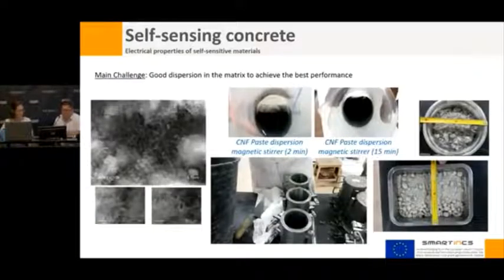The incorporation of a component into the cement matrix to provide a new property very often leads to a modification of its properties. Additives such as CNT and CNF would preferably modify electrical resistance properties, but microstructure and, as a consequence, mechanical properties can also be affected, in both fresh and hardened state. If a lack of dispersion or interfacial interaction with the cement paste occurs, the effect can depend not only on the additive content but also on the characteristics of the composite matrix. The introduction of admixtures with large aspect ratio forms reduces the mechanical properties of the matrix, especially if proper dispersion is not carried out, as we saw in the last presentation.